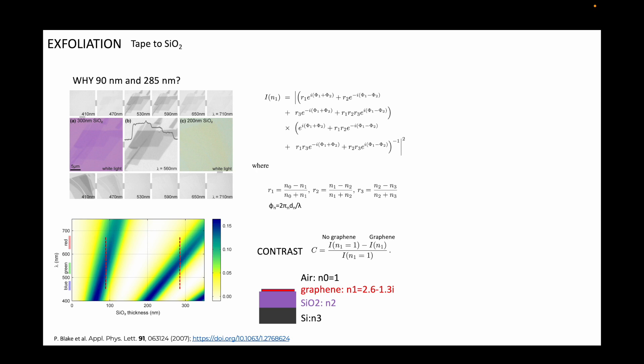The optical equation is quite easy to understand, so if you have different materials or substrates, as you will see later on, you can quickly find out what the thickness and wavelength of light are needed to maximize the contrast. The I here is intensity, R's are the comparison between the indices of refraction between neighboring layers, and Phi's are the phases resulting from the thickness of the medium with respect to the wavelength of light.